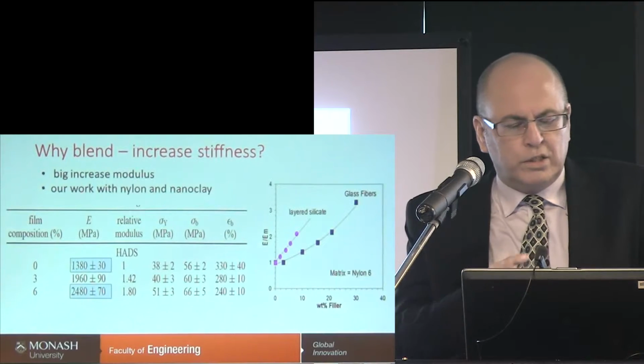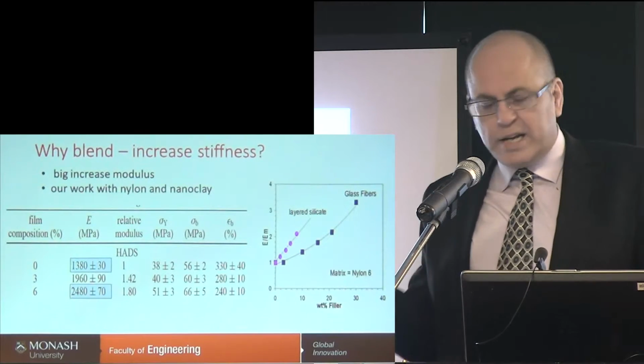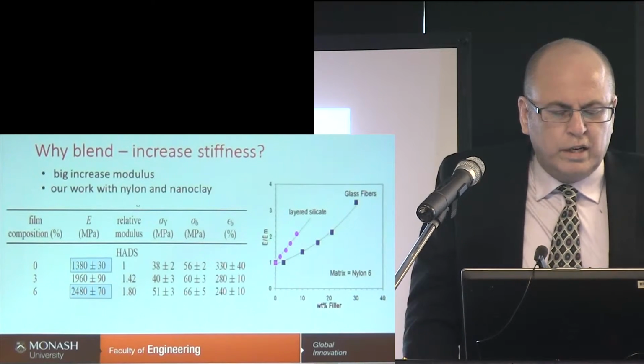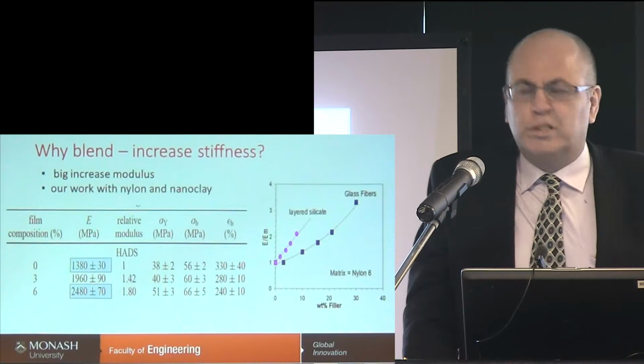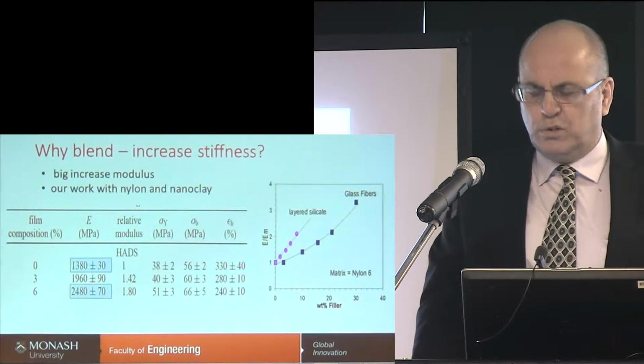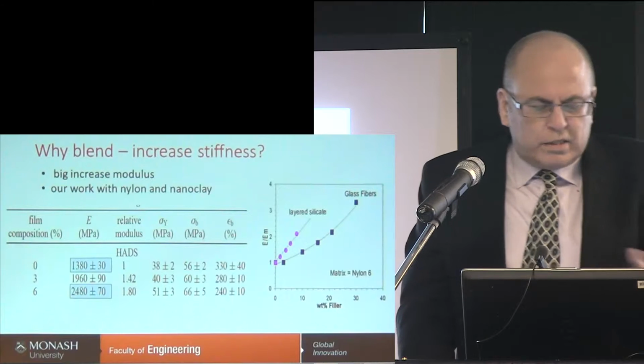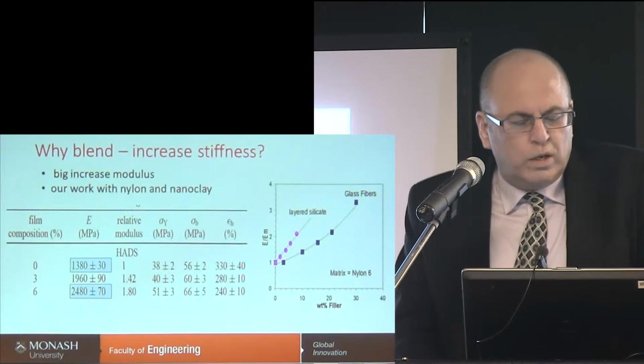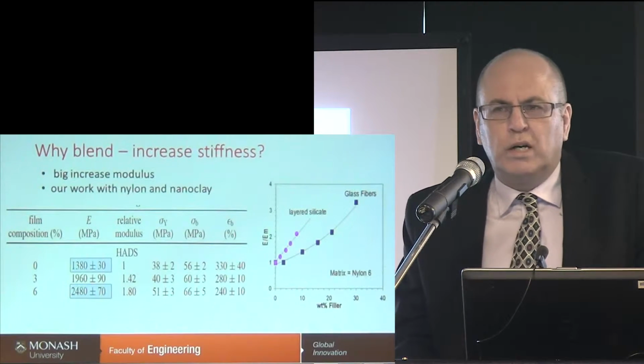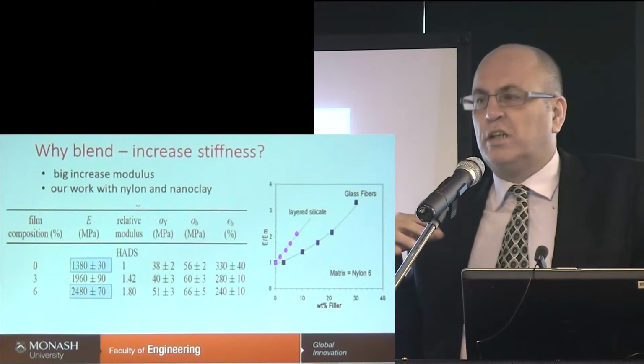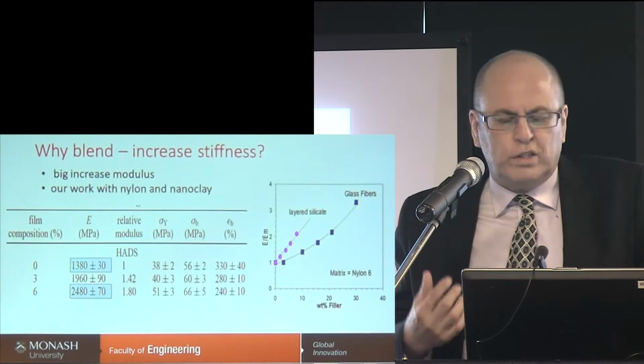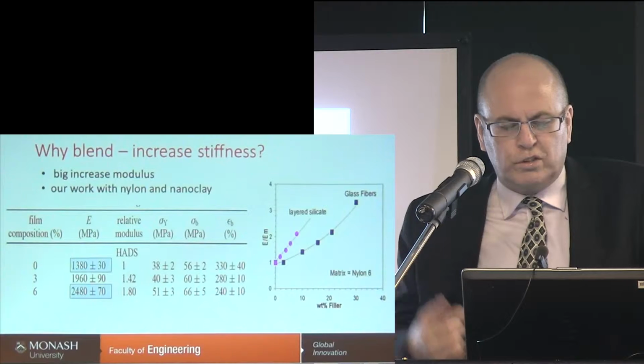So why blend? This is some work we did with nanoclay in nylon. You can see that only a couple of percent, in this case 6%, almost doubled the modulus of the material. And 3% also increased it substantially as well. And so this is an example of where nanocomposites at a high surface area can use very small amounts of material to achieve desirable results.